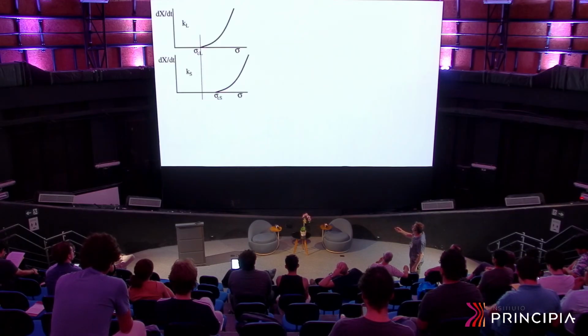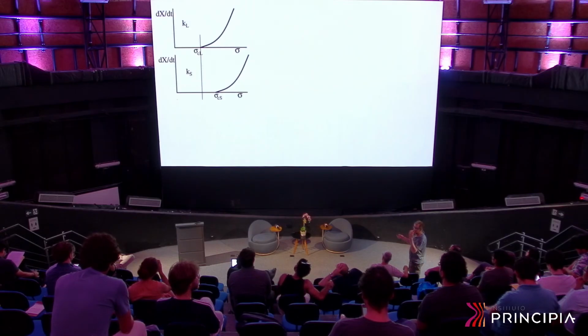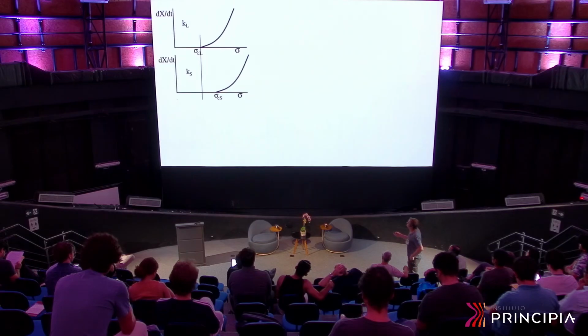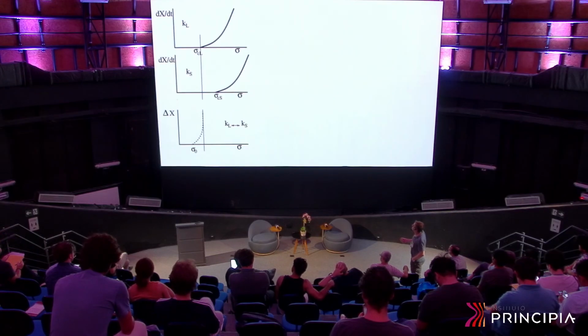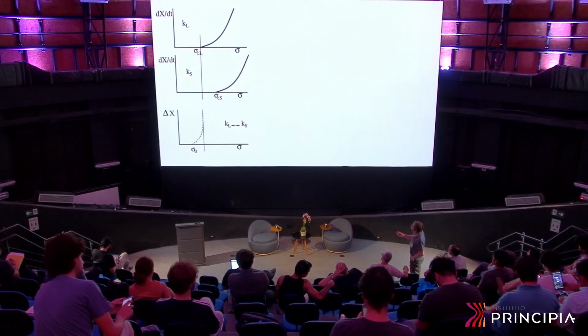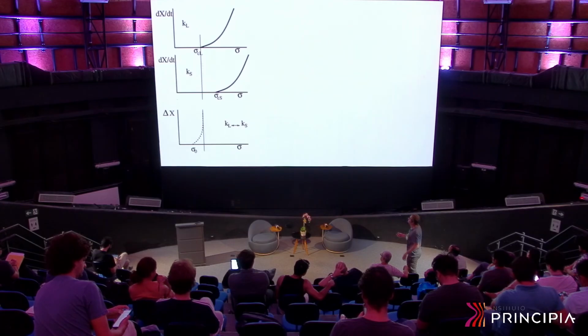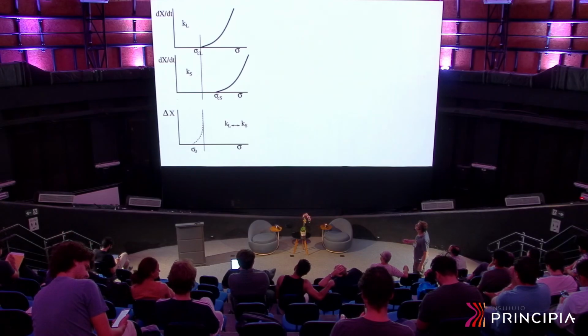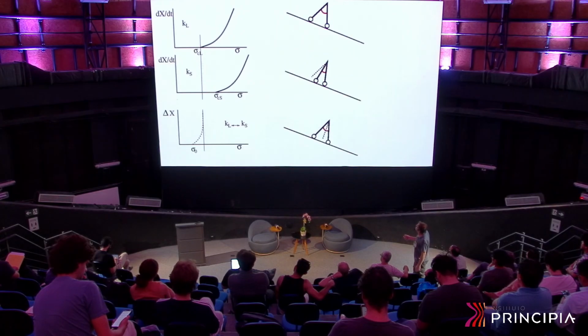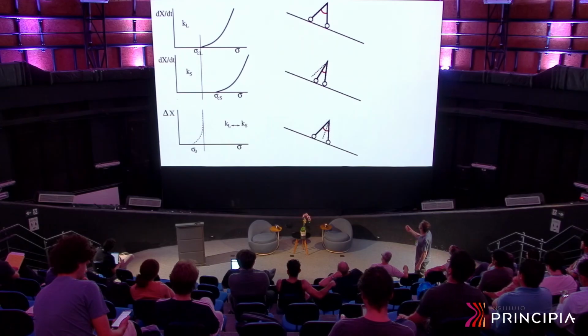So if I change this value of k between a large value and a small value, we expect that the flow curve of the system moves, as I said before. Actually, for a small value of elasticity, the critical stress is larger because the system can accommodate better to the disorder potential. But the non-trivial finding is that, when cycling between a large value of the constant k and a small value, in addition to the curve moving rigidly from one configuration to the other, we obtain a global displacement of the system by a fixed quantity of the typical variable x. And of course, this depends linearly on the number of cycles that I do. So this is essentially nothing more than what I described in the toy model here. This delta x is nothing more than the displacement of the toy from here to this configuration.